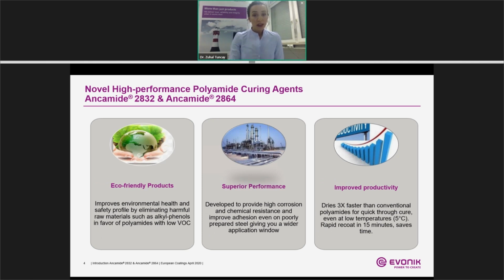So our role as curing agent supplier was to provide our customers with the best technology solution to meet these emerging needs. With that motivation, we developed a new platform for high-solid polyamide curing agents, which are eco-friendly. Those products exhibit low or zero emission. They provide excellent long-term performance with improved corrosion and chemical resistance. And because these new products are 3 times faster than the conventional polyamides, they provide faster return to service even at adverse curing conditions.